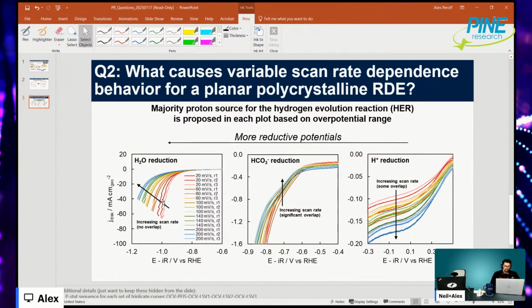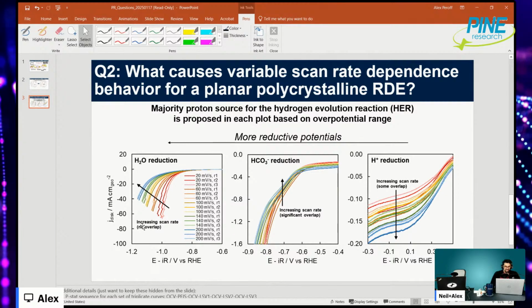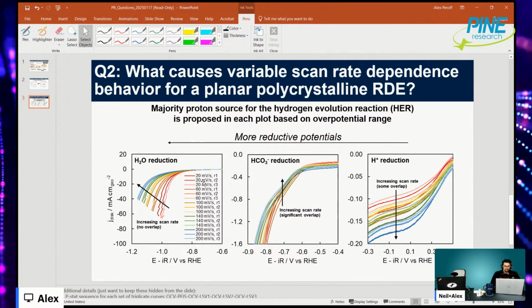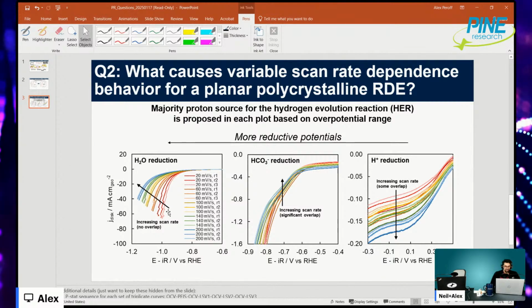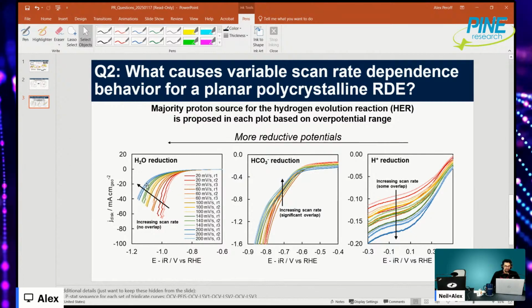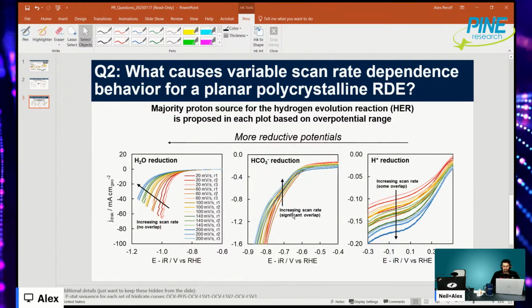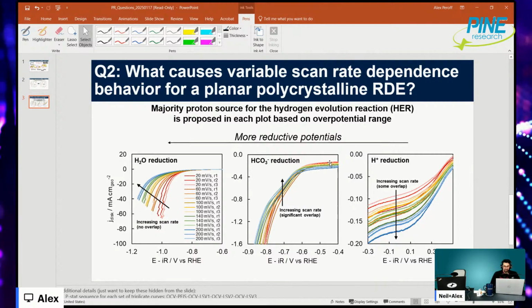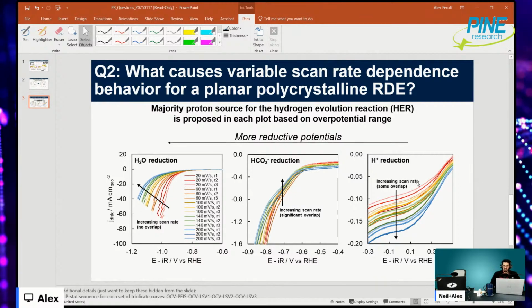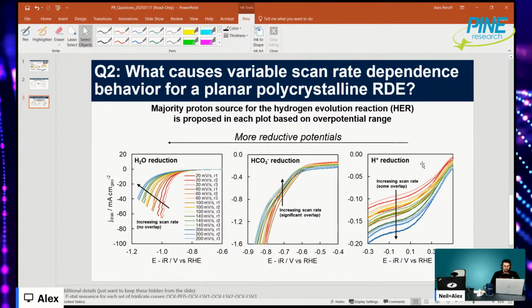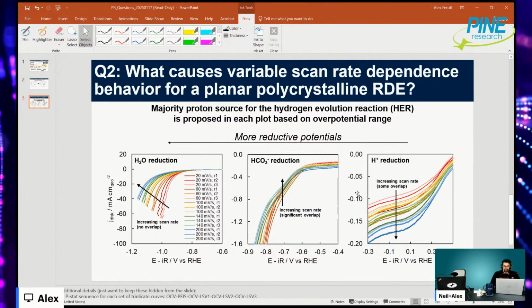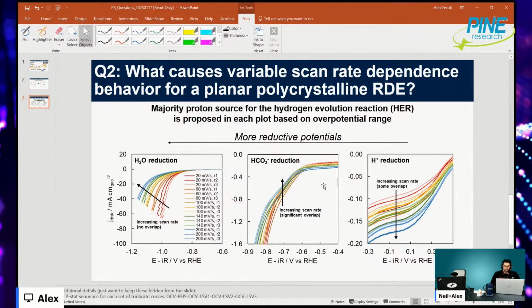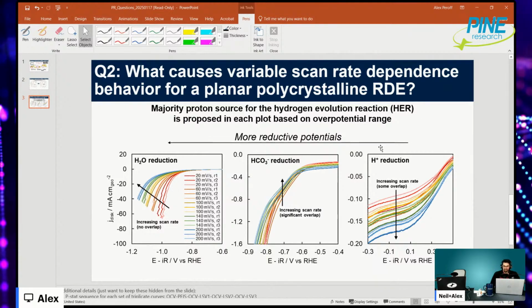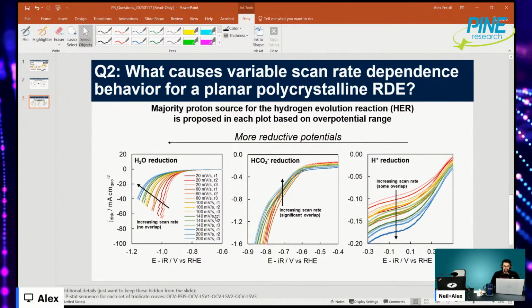One thing that the person observes is that as they increase the scan rate, going from 20 millivolts per second to 200 millivolts per second, there seems to be very little overlap between these curves. Conversely, when they increase the scan rate, there seems to be overlap between these curves, and they see some overlap as they increase the scan rate for H plus reduction. So you get somewhat of an inversion between these as they change the scan rate.